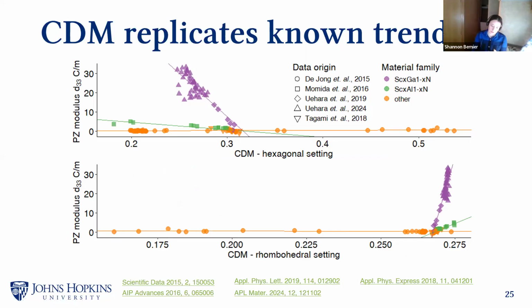And the interesting thing here is this would imply that further away from a cube shape gives you a better piezoelectric modulus. But I would take a close look at this line here, which is really nearly vertical and suggests more that we may be approaching some kind of ideal non-cubic structure, which will produce the highest piezoelectric modulus, and not that you could extend the original trend infinitely to zero until eventually your hexagonal structure compresses so that the C and the A are exactly the same value. So that's an interesting thing to note.